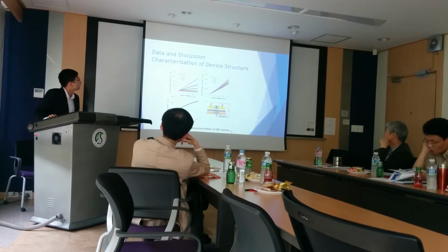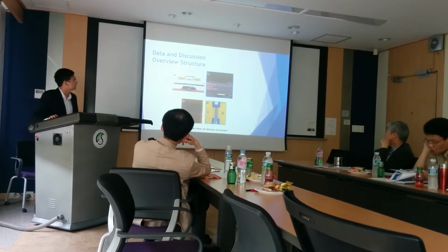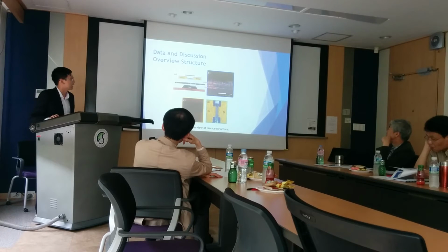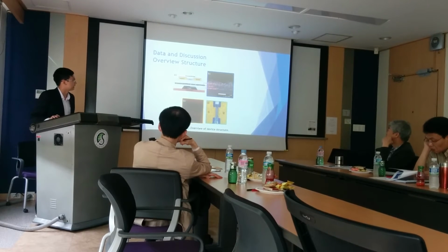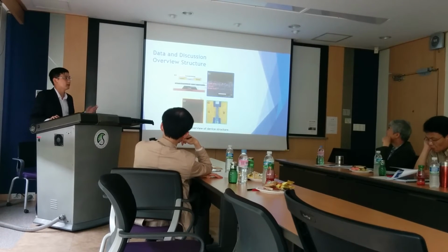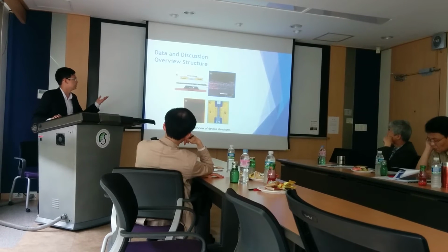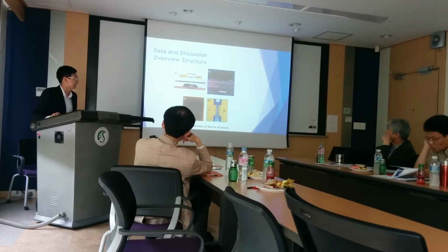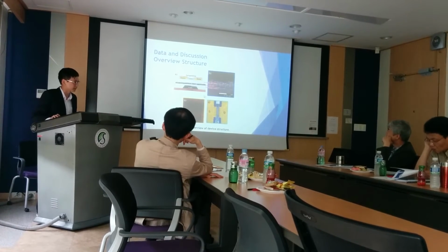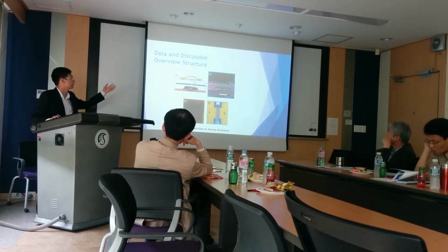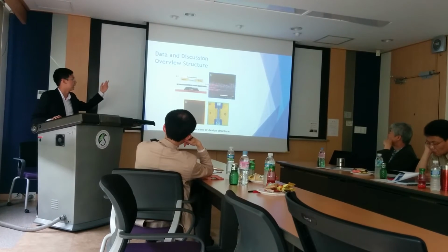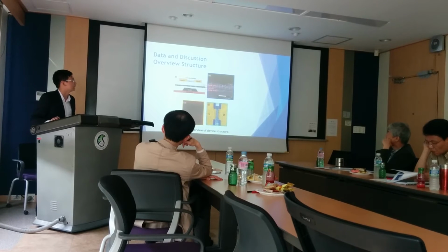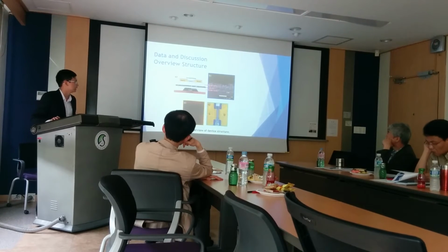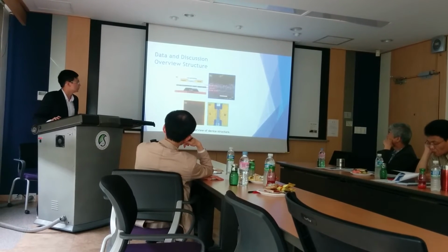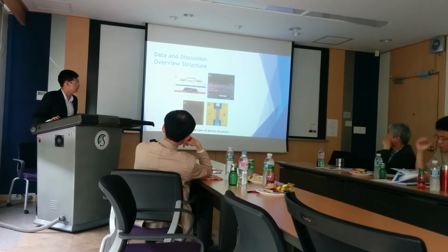This is the overview structure of the MEOFET device. In the cross-section, to develop the MEOFET, we deposit nickel as the gate electrode on the polyimide substrate. Then we deposit the pentacene channel, source, drain, and encapsulation by the thermal evaporation method. This is the ME composite we checked by the SEM image.